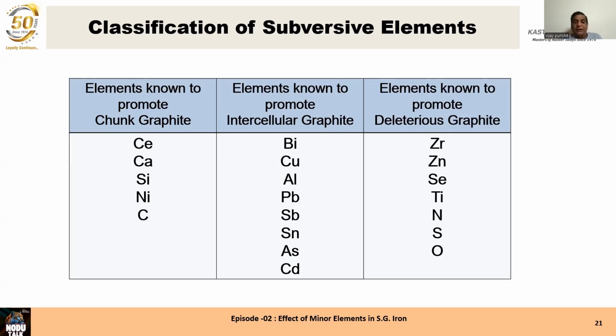Make sure that you use rare earth containing ferrosilicon magnesium for the magnesium treatment. If you are making very, very large castings, then I'll give you a tip. Most people avoid the deleterious effects of these elements in very large castings by taking 50% ferrosilicon magnesium with cerium and 50% ferrosilicon magnesium without cerium. So both of them put together will give you casting without deleterious elements and without chunky graphite. Because in heavy sections, if the cerium is more than 0.025, you get chunky graphite.